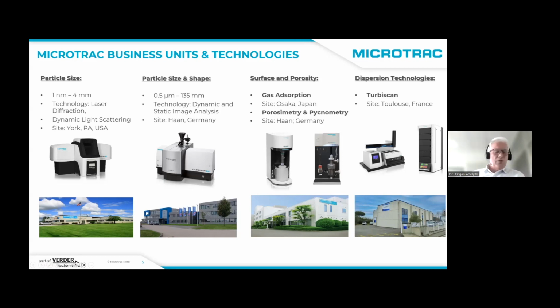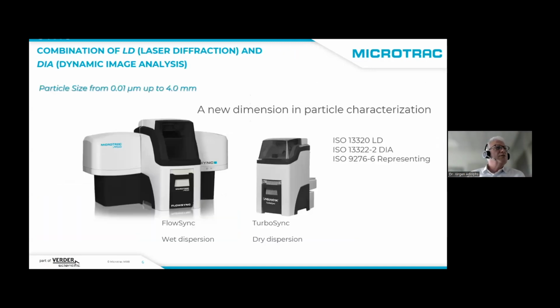I will come now to a first part for the particle size characterization, and in combination with a laser diffraction device and a dynamic image analysis. So we can cover particle sizes from about 0.01 micrometer up to 4 millimeter with these devices. We can do these measurements in a wet dispersion or in a dry dispersion. These are also working according to these ISO standards for laser diffraction, as well as for the dynamic image analysis, and of course for the representing of the results of the both.